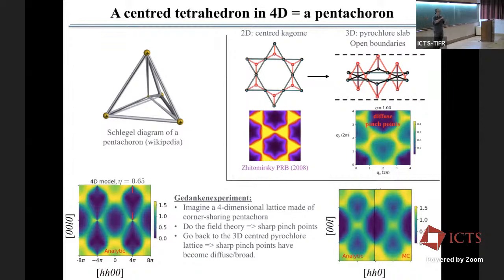Another way to see it is that if you see the pyrochlore 3D lattice as 3 copies of U1 gauge field theory, then the central spin, you decompose X, Y, and Z components as 3 scalar charges. And these scalar charges act like a local disturbance and locally break the divergence condition. And so by breaking it, you get exponential decay. And so it is not a Coulomb phase. It's a kind of 3D slab of a 4-dimensional Coulomb phase. But because of the open boundaries, you don't have algebraic correlations.